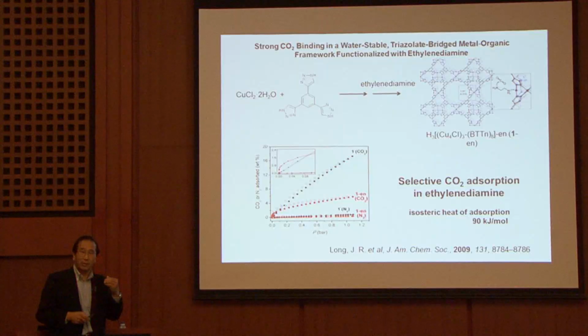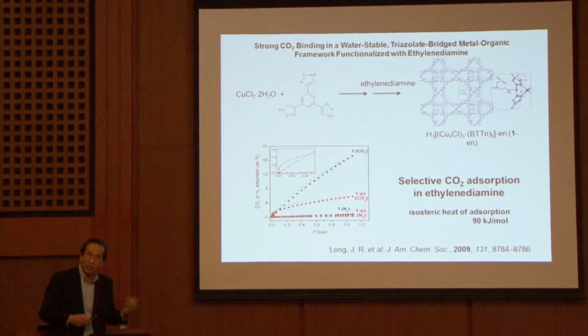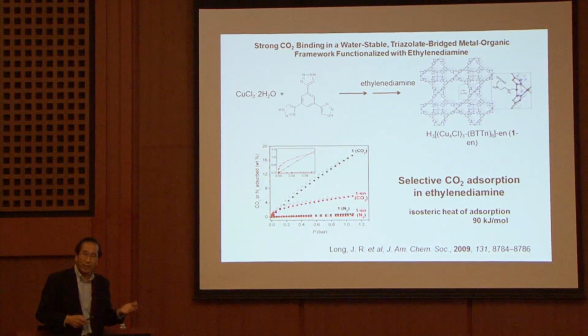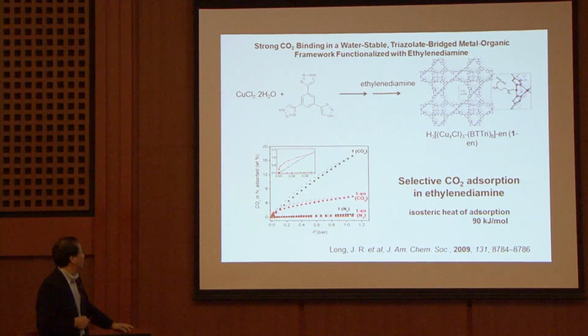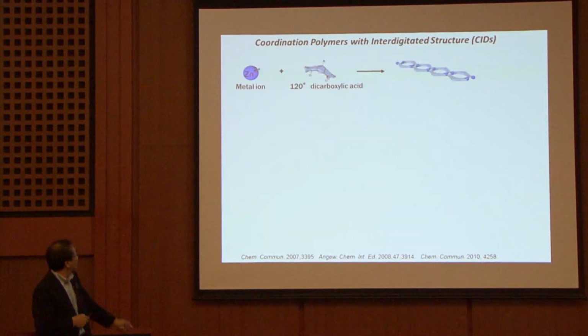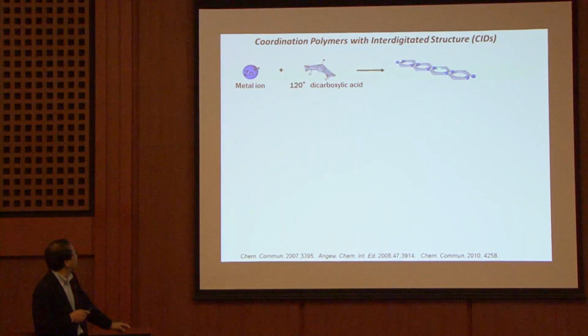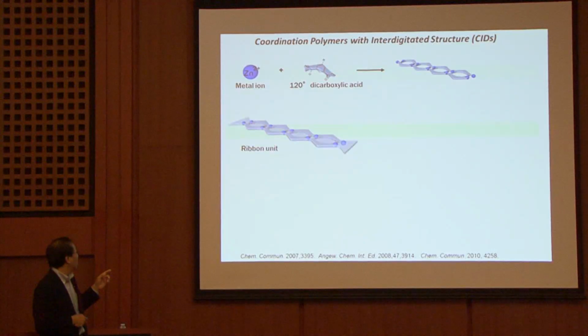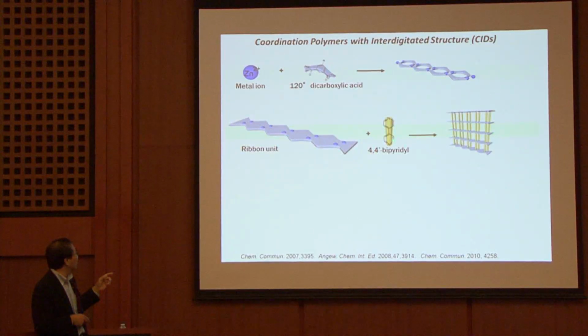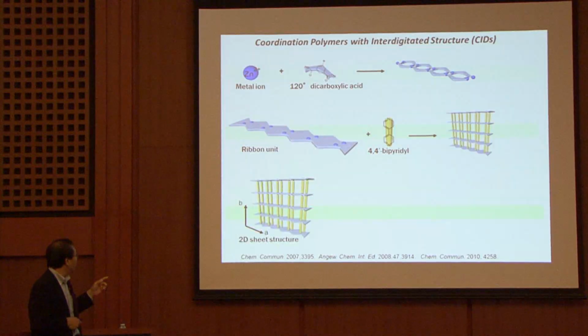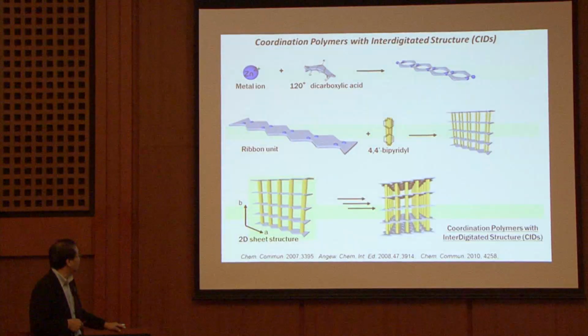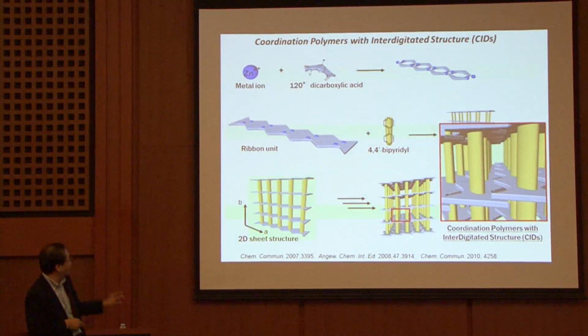Reduce the pressure to very, very low, in high vacuum condition. An energy consuming process must be used for these materials. So we synthesize this framework just like this. Zinc ion, by using this ligand, gives a ribbon. Ribbon gives this kind of layer by using the bipyridine, and this layer gives a stacked structure like this. Okay? This is the framework.